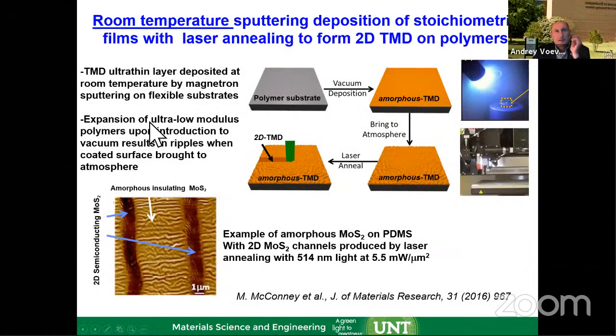And now ultimately, if we drop the temperature all the way down and we want to produce these fabricated devices on a polymer substrate directly, then the temperature is not enough to make any crystalline material at all. So you lock atoms in place where they arrive. They don't have the ability to hop around and form a crystal. You make amorphous material. And this is where the combination with the laser becomes very, very useful.